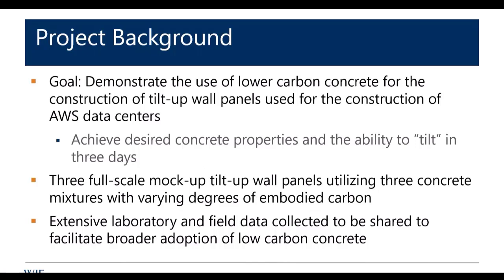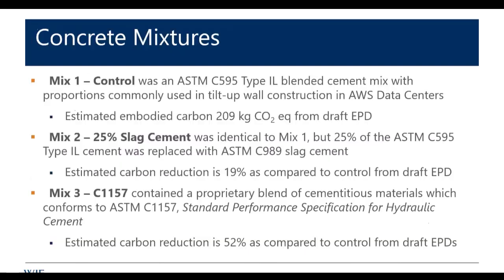But our goal was to demonstrate in a real world application using traditional materials, a slight stretch, or just something a little different, but within current technology, and then a big goal, so 3 different materials. And basically what we did is full scale tilt-up wall panel construction based on AWS design and with the desire to achieve tilt-up in 3 days, because 3 days is critical for them to be able to move their construction along. You can't hit 3 days, not happening. We did, like I said, 3 full-scale mock-up wall panels utilizing 3 different concrete mixtures. A lot of laboratory work was done, so we'll talk about Labcrete, and then we're going to talk about construction.